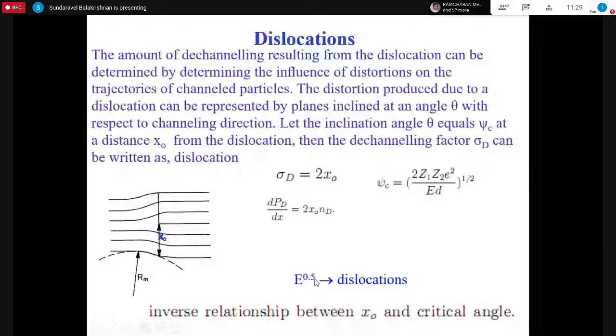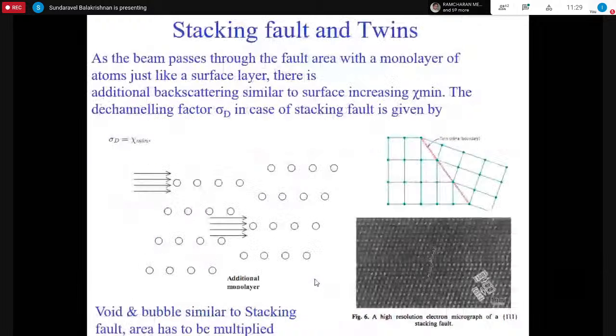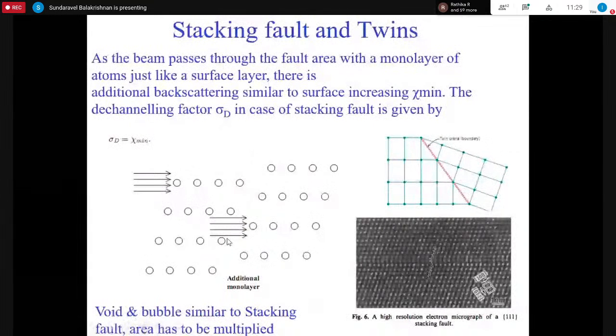When you look at the stacking faults, when the beam is falling, the beam will see the presence of the dislocation as a new surface, and whatever scattering happens is similar to this chi minimum. This sigma d is proportional to this chi minimum, and chi minimum value doesn't have any energy dependence. So you don't have energy dependence in this one.